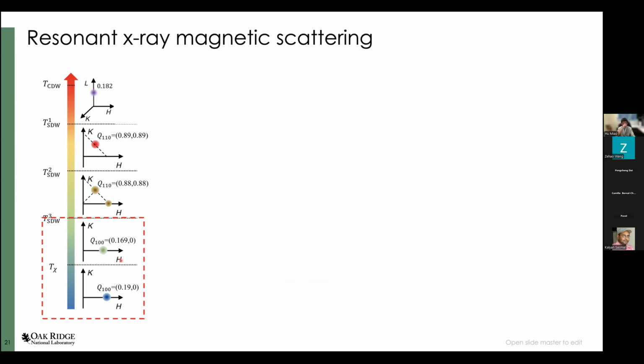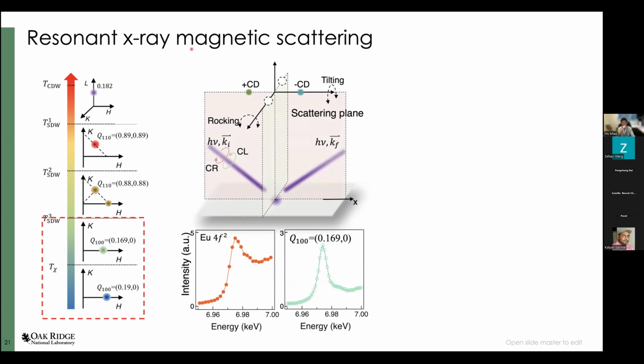In order to study the magnetic phase, the technique we use is resonant X-ray scattering, magnetic scattering. So here is the geometry. To do this, you need to tune your photon energy to match the energy difference between your core electron and the unoccupied state. Once in that regime, you can be sensitive to magnetic structures. Here, I just show you the resonance fluorescence scan, and we can observe a quite clear europium L-edge resonance.